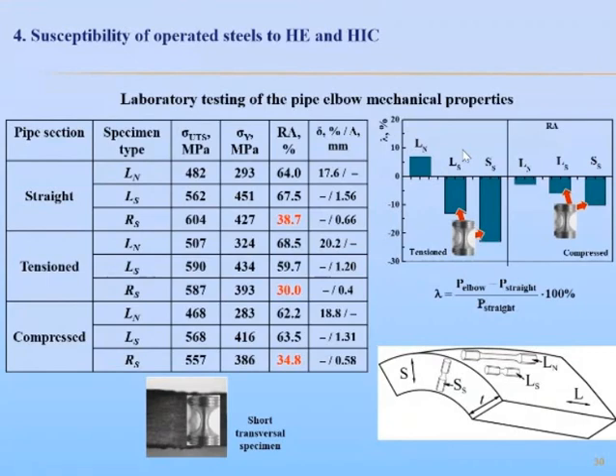Moreover, the highest decrease in reduction in area values was inherent to the steel of the tensioned pipe elbow section compared to the straight pipe one. And it should be noted that to determine the plasticity characteristics of the pipeline steel with damaging susceptible to hydrogen-induced cracking correctly, notched specimens